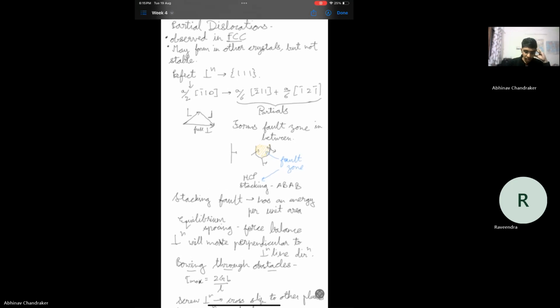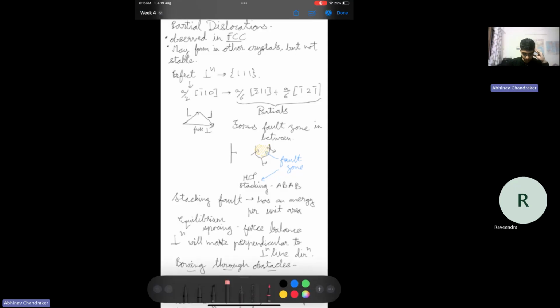So for FCC, we know that the most favorable slip system is the 111 family of planes and the 110 family of directions. And 110 is the Burgers vector. And when it splits, it can split into a/6 [2 bar 1 1] and a/6 [1 bar 2 1 bar], so it's split into two partial dislocations. And this will be favorable when you use Frank's rule to evaluate this. You can try that to see how the energy changes due to splitting of the dislocation.